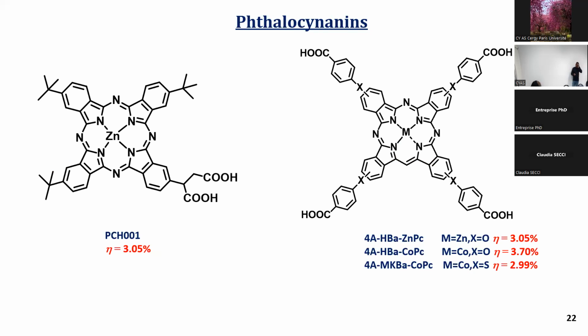They introduced phthalocyanine molecules. The phthalocyanine molecule PCH 001 reached an efficiency of 3.05%. There are also molecules with zinc, cobalt and other metal complexes, and the cobalt phthalocyanine molecule reached... I'm explaining only a very few molecules. It's a macrocyclic ring with an extended conjugation system, and these molecules' absorption reached the near IR region. We increased absorption from the UV-visible region to the near IR region, but the efficiency they reached was very low. To overcome this, we again looked inside the molecules.